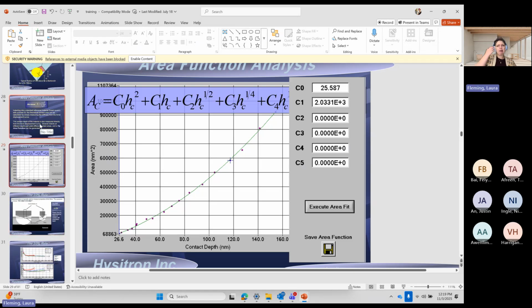So our software goes up to 6 coefficients. We typically do 3 or 4. We tie C naught for a generalized tip area function. There are some exceptions here. I have two ends of the spectrum. I have a customer who is only doing thin films and he only indents like 20 to 30 nanometers. When you're doing that kind of indentation, the tip is never going to act like an ideal Berkovich probe. It's going to be blunted. And in that case, we let C naught vary. And we only do indents in the contact depth he is interested in. So we only do indents in the fused quartz at that very low value to get an accurate tip area